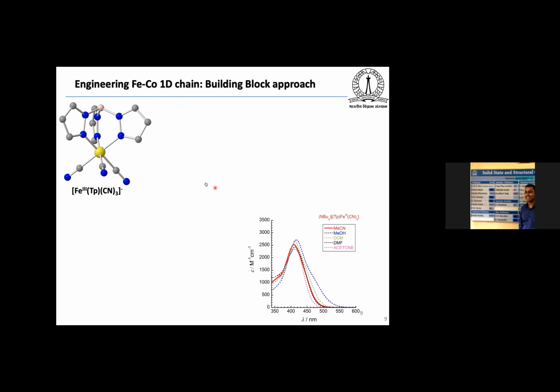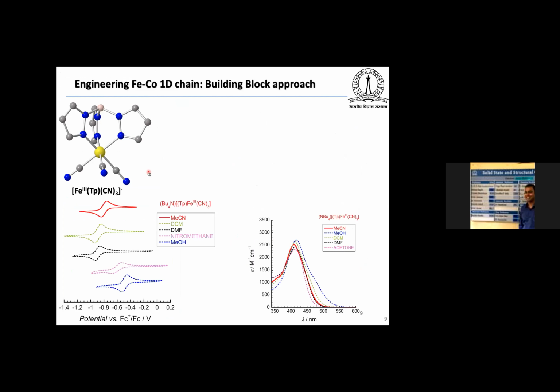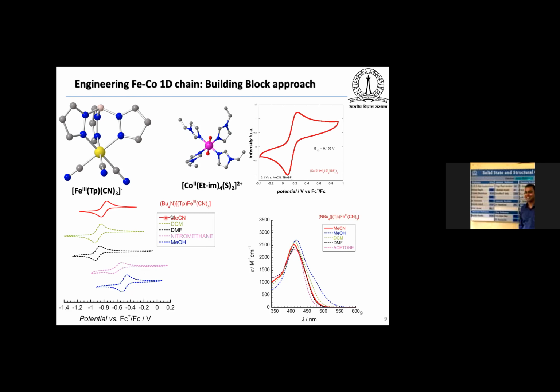So why do we choose this iron TpCN3 building block? This is a very interesting property. You can see that just by changing the solvent polarity, you can tune the E1/2 value of the system. So here, the E1/2 value is roughly around 0.8, minus 0.8 volt reduction potential in acetonitrile solvent. And you can see in methanol, the E1/2 value changes by almost 0.25 volt. And here also we choose this cobalt ethyl imidazole ligand, and you can see that the E1/2 value is roughly around 0.15 volts. So if you see the difference, that is roughly around 0.96 volt, which is almost close to 1 volt.